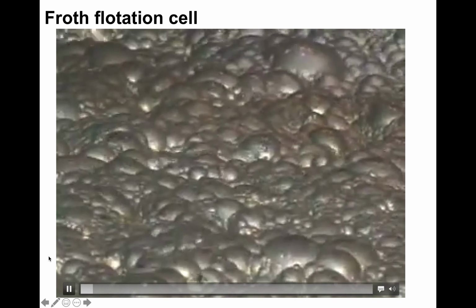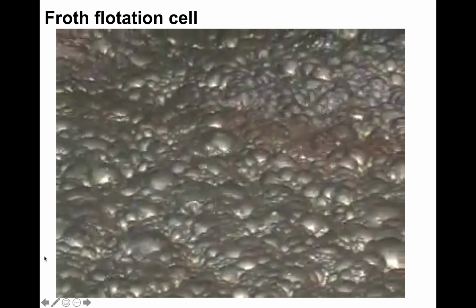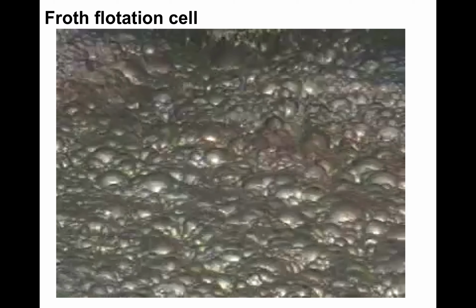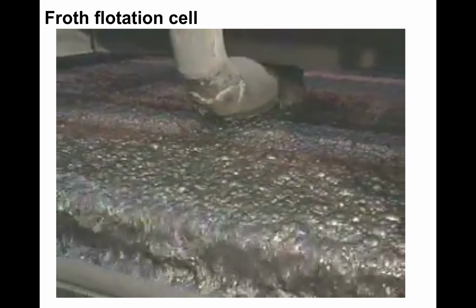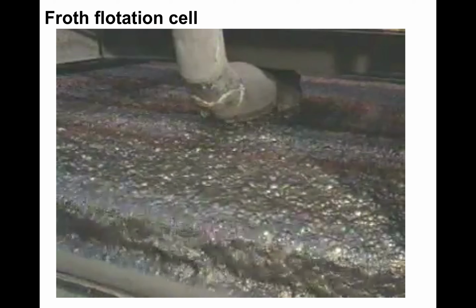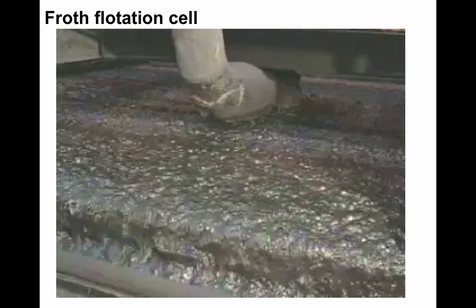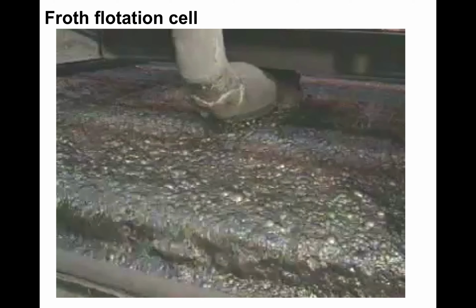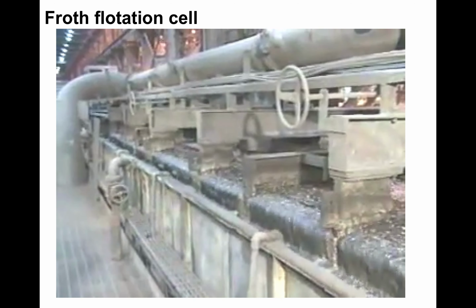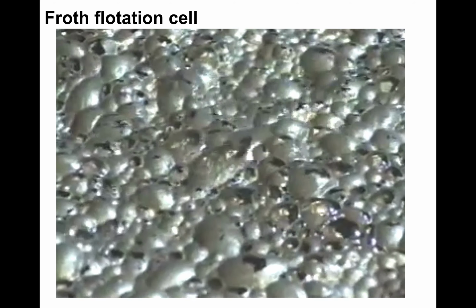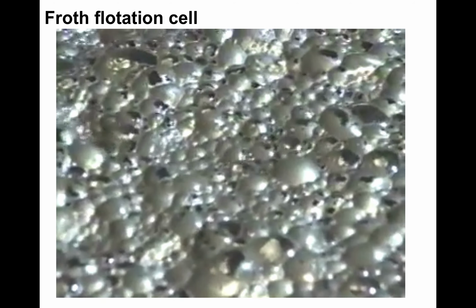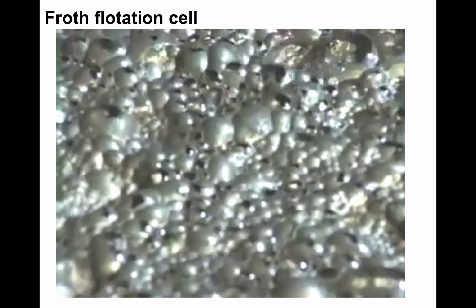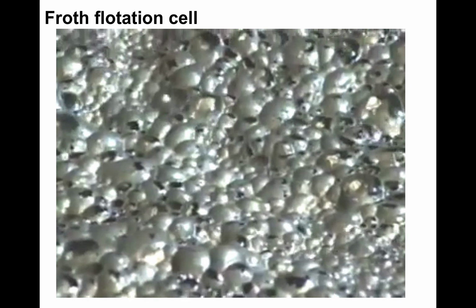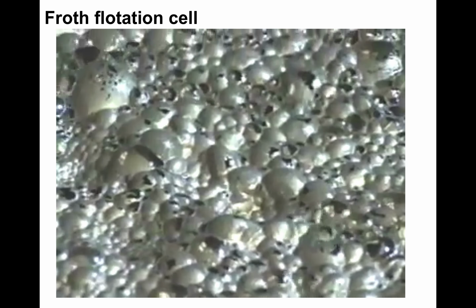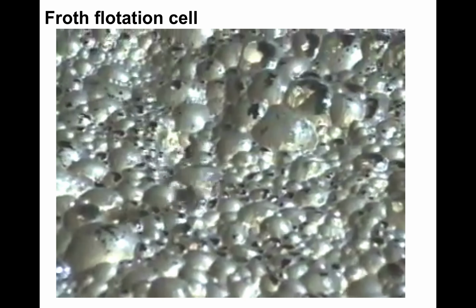The froth in the first few cells of a bank is often heavily loaded with hydrophobic particles. The froth appears dense and heavy. The bubble size is small due to the stability imparted by the particles. As you move down the bank, the appearance of the froth will change. There are not as many hydrophobic particles available to float, and thus the froth loading is lower. Windows appear and froth stability decreases, resulting in larger bubbles, many of which will burst.